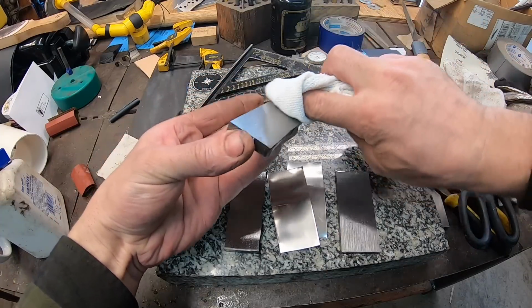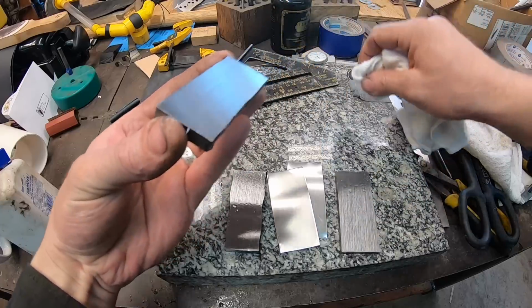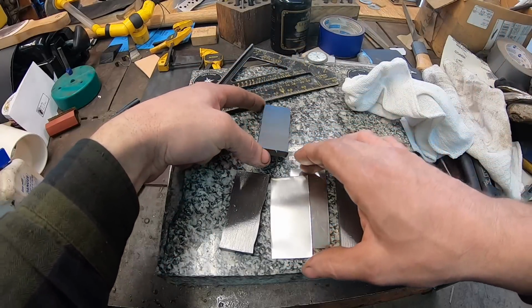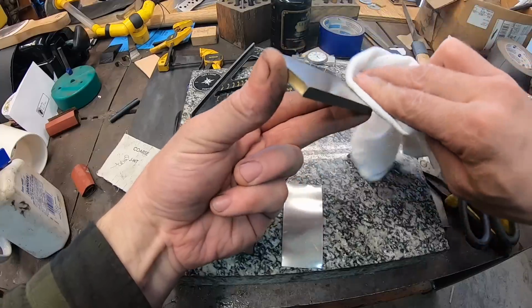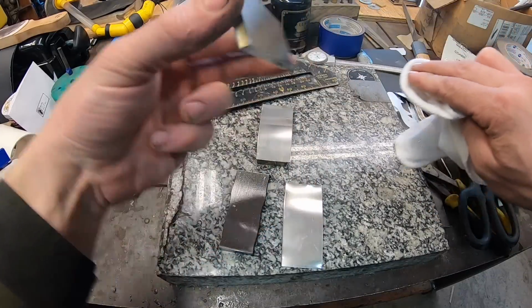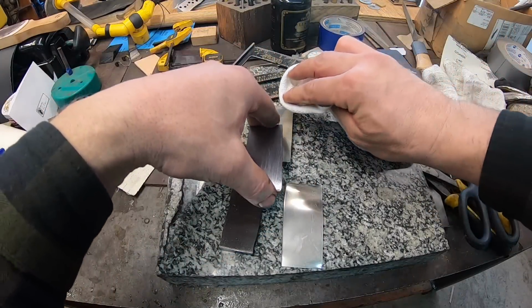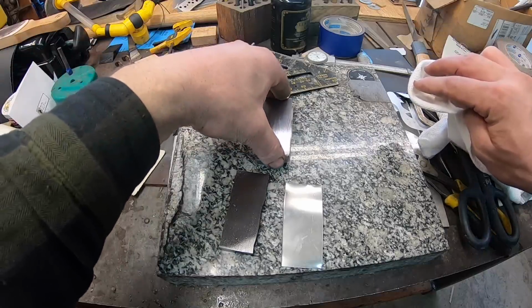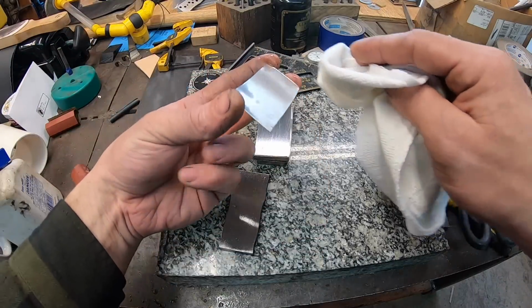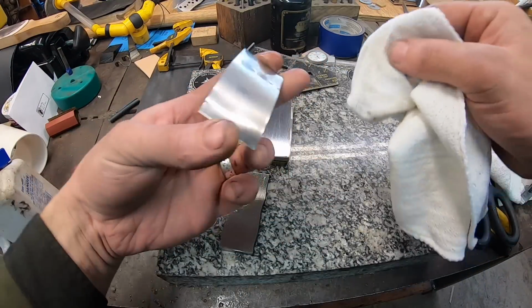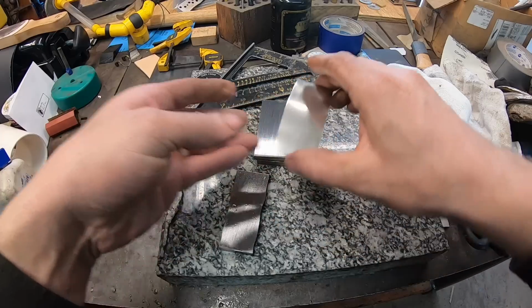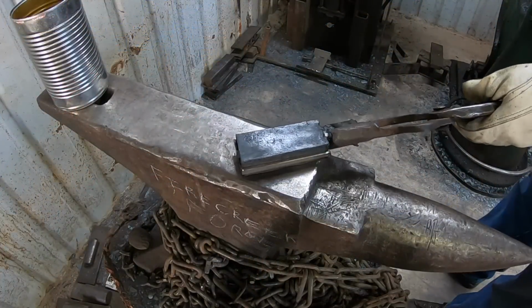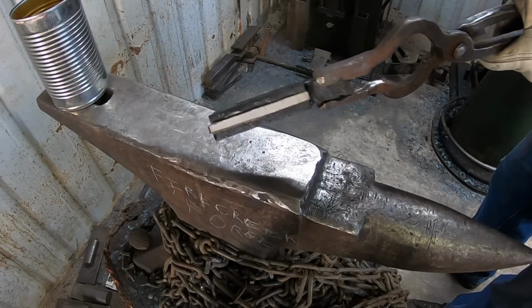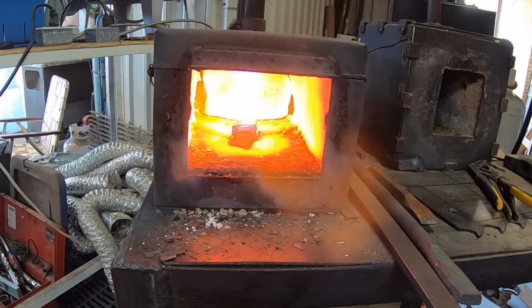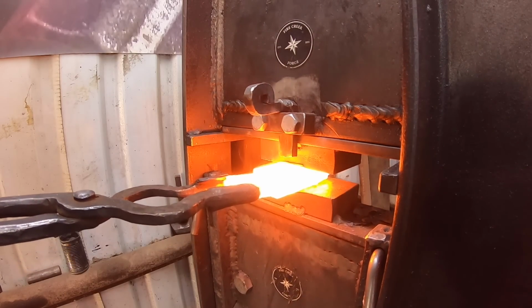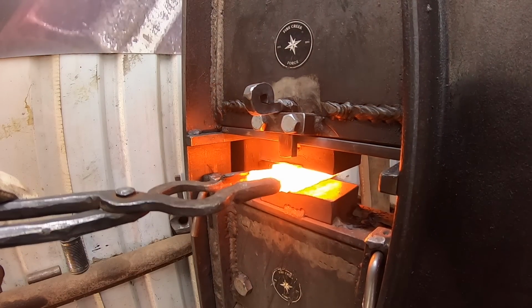So we've got our bar forged out there, and it's now about 170 layers, and we can go ahead and assemble our final billet. This is the billet that will be forged into the actual blade. So you can see that centerpiece I just put down, that is 52100 high carbon steel. So we've got 52100 in the middle, nickel on each side of that, and then our nickel and 1045 stacked cladding.